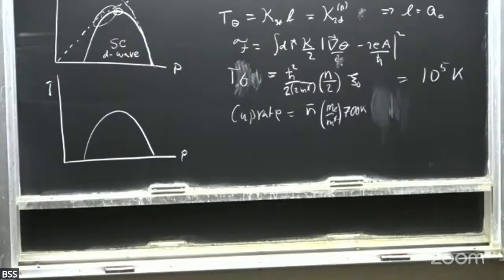So one thing one can do is to look at the gap in angle-resolved photoemission. Now, that has two problems. One is it can only be done with really high precision in the Bisco family of cuprates, because these are the only ones that have the really nice surfaces that allow you to do this sort of high precision ARPES. The other is that it's a surface probe, and so you can always ask yourself whether what's seen, even in Bisco, is special to the surface. I think there are very good reasons to think these aren't serious. I'm not going to worry about them. But, you know, since I'm young and impressionable, I'm trying to be realistically honest.